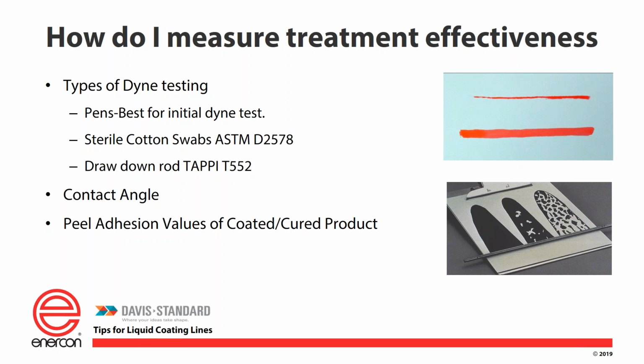A little bit of a corollary test to that is the TAPPI T552 method, which is using a drawdown rod. Now, in our slide here, on the right of the slide and the lower picture there, you'll see the drawdown method. I am a big fan of this method, and I'll tell you the reason why. In that slide, you'll see a piece of film on a clipboard, and just for the sake of conversation, let's say that the far left drawdown is 38 dynes, the middle one is 40 dynes, and the far right one is 42 dynes. You take that number 4 or number 6 Meyer rod, you draw them all down at the same time. So you have an instant comparison between each drawdown right then and there. You don't have to go out and get another pen and remember what the last one looked like or anything like that. The Meyer rod does a great job of smoothing and drawing down an equal amount of coating